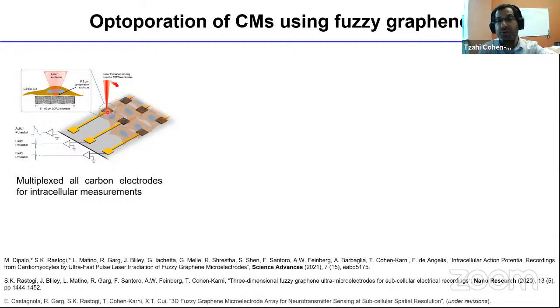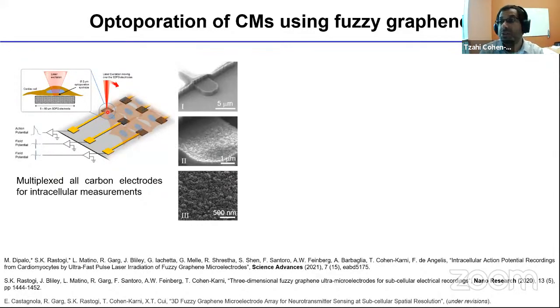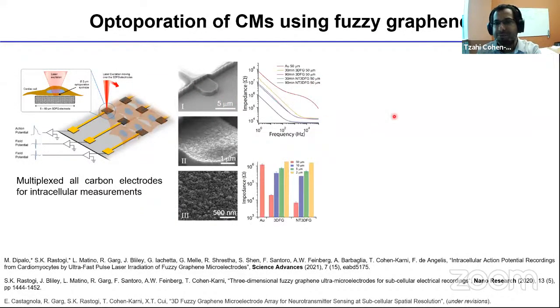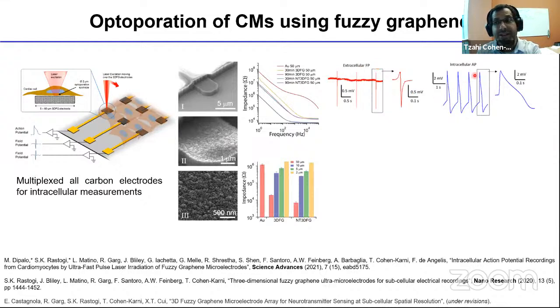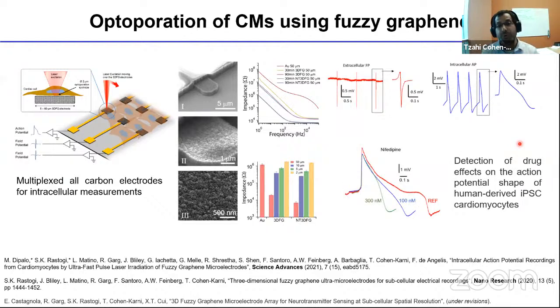So we are using an ultra-fast laser to raster on the electrodes, and we are using such conditions that we generate cavitation. So it's a different process as compared to the photothermal stimulation. This cavitation generates tiny holes in the cell membrane and gives us access to the cytosol, and then we have intracellular-like action potentials. So this is how the multi-electrode arrays or fuzzy electrodes look. Again, these are 5 micron by 5 micron electrodes that we are generating. I'll skip through this. So this is extracellular field potentials, and then you shine pulses of laser and you get these intracellular-like action potentials.